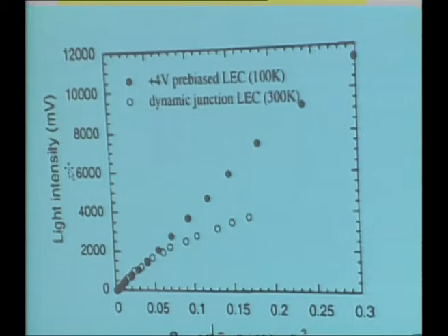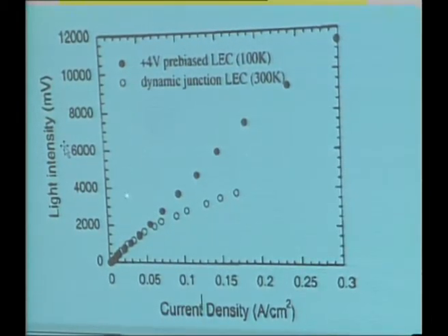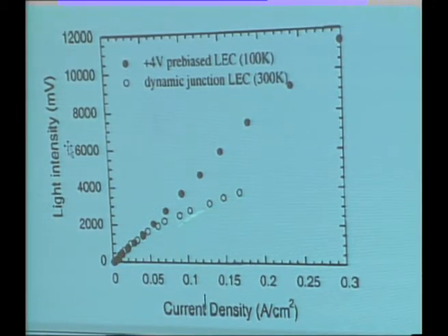At room temperature, where the ions can move, I haven't emphasized this, but at room temperature where the ions can move and you've got an active electrochemical cell, you have all the difficulties of side reactions of electrochemistry. The devices don't last very long. They decay very rapidly. But if you have a frozen junction, then you can push the voltage up much higher, push the current up much higher.